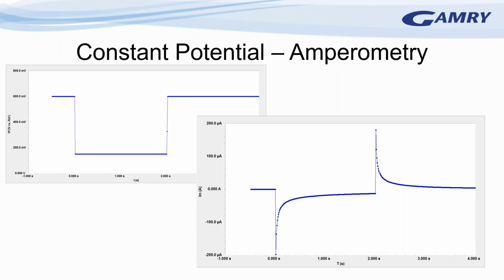So in a constant potential or chronoamperometry type experiment, we might start at one potential level, step the potential to another for a certain length of time, and then step the potential back to the original potential, or maybe another potential. And the resulting current is shown on the right here, where you get a current spike that decays to a steady state. And then when we step back, we re-oxidize or re-reduce whatever was oxidized in the first place, and we get another current spike that goes to a steady state.